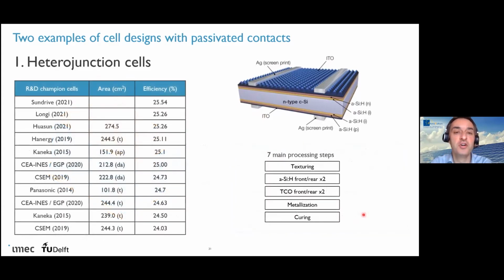Over the years, especially recently, very high efficiencies have been reached. The record at the moment is by an Australian company, at 25.5%. That's pretty high, and there are already rumors that people have reached 25.8%. So you can reach really very high efficiencies with this kind of cell. It's also still relatively simple to process—you only need 7 main steps.